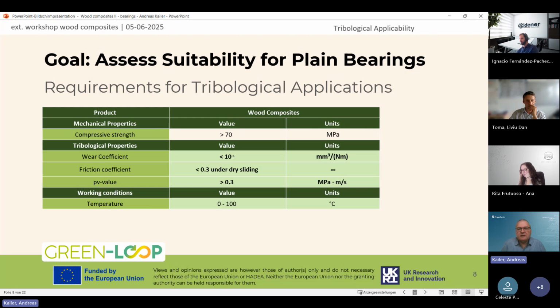Wear coefficients was very important. This describes the volume loss per load and sliding distance, which should be lower than 10 to the minus 5. Friction coefficients in dry sliding lower than 0.3. And a so-called PV value, which is a product of contact pressure and sliding velocity, should be larger than 0.3 as an application limit of this material.